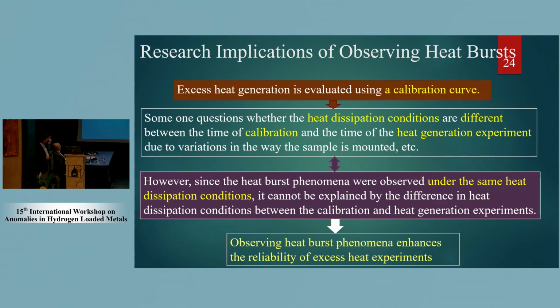And one more point, the research implication of observing heat burst. Excess heat generation is usually evaluated using a calibration curve between the nickel bulk and the multi-layer thin film sample. Someone questions or doubts whether the heat dissipation conditions are different between the time of calibration and the time of the heat generation experiment. But since the heat burst phenomena were observed under the same heat dissipation conditions, it cannot be explained by the difference in the dissipation condition between the calibration and heat generation experiments. So observing heat burst phenomena enhances the reliability of excess heat experiments.